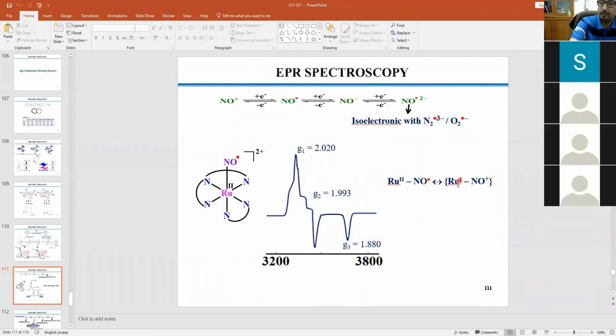So you now have an unpaired electron over here, t2g6 eg1, and that is giving some amount of anisotropy. Now the question is, is this resonating form correct? My answer is no. Because these resonating forms show that they are mostly 50-50% in ratio. But actually what is happening is an 80-20 ratio. And that could be estimated by calculating the spin density of this molecule: you will see 20% spin on the metal side and 80% spin on the ligand side. That means this is the dominating electronic form and this is the minority contribution.